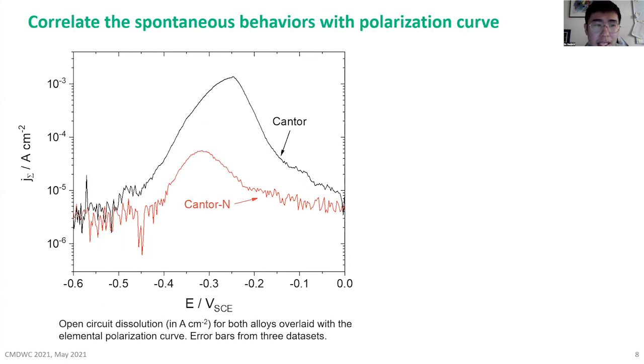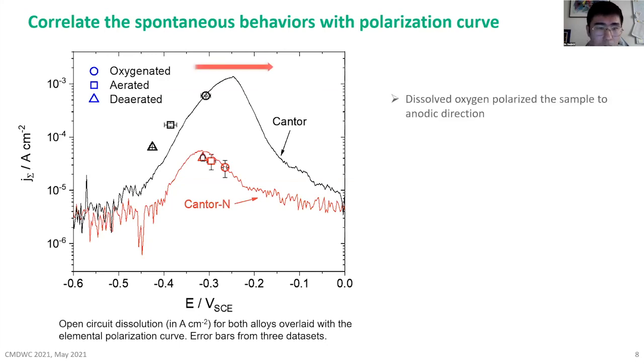So this slide, the last slide, we can correlate the spontaneous corrosion behavior with the polarization curve. In this curve, we show the elemental current taken from the polarization curve for both alloys. And we can overlay this curve with the open circuit dissolution rate in all three electrolytes for both alloys. And we converted the unit into elemental current. We can see when we increase the dissolved oxygen in the electrolyte, for both alloys, we polarize it into a more anodic direction. But this exerts different influence on these two alloys.